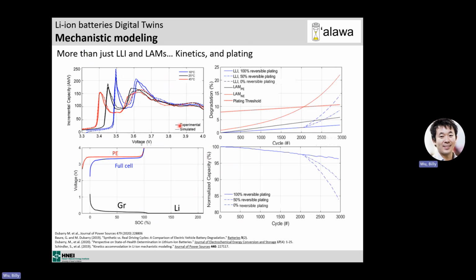Also, we can change the kinetics. We can predict it, and we can play on the reversibility of that plating. If plating is irreversible, you're losing lithium. So that's a loss of lithium inventory. Plating by itself does not induce any capacity loss. We're doing half cell all the time. We can plate and strip lithium easily. Plating by itself is not a degradation. Plating is not a degradation mode. The degradation mode is the loss of lithium inventory, because that lithium is lost. We don't know where. Mostly it's dead somewhere on the electrode, and it could be reconnected under some cases.